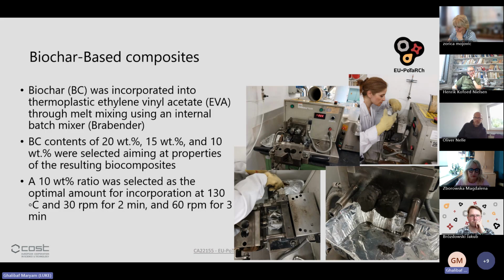The main thing, which was really very challenging, was that the essential part of the process was thorough cleaning of this blender after each batch. This step was critical to avoid cross-contamination between different biochar samples and to make sure that the accuracy and reproducibility of the results are really good. And that was a very time-consuming process, but at the end I could make a total of 5 composites, including 1 reference composite without the biochar and the other 4 with the biochar.